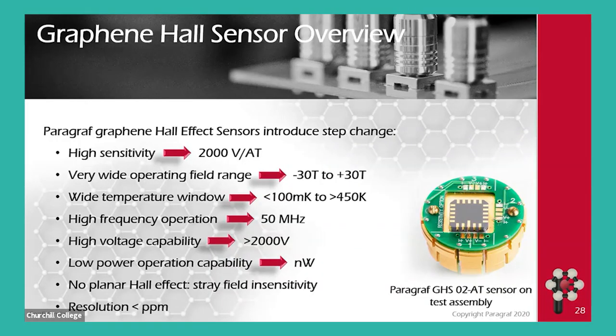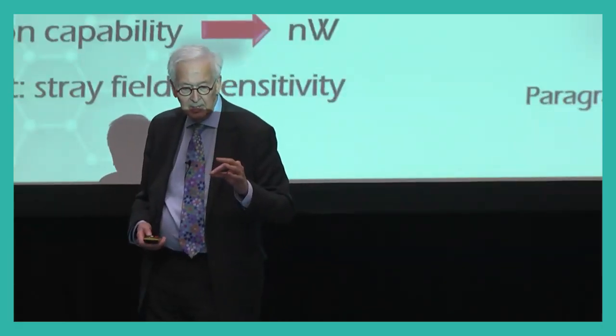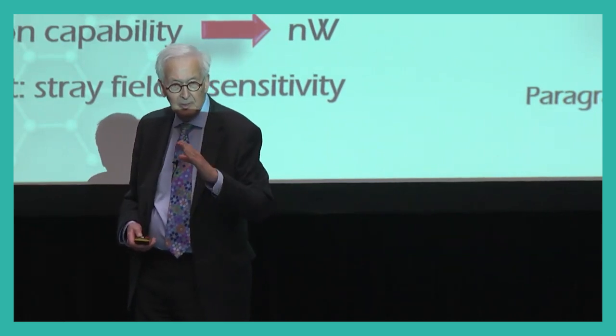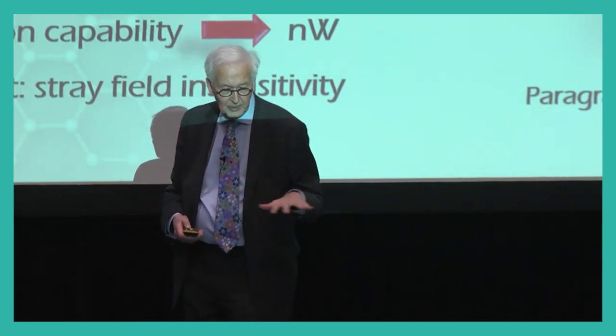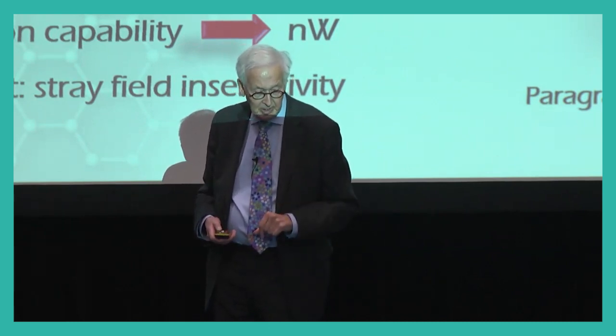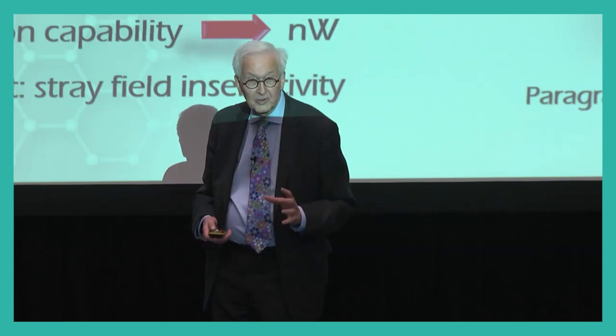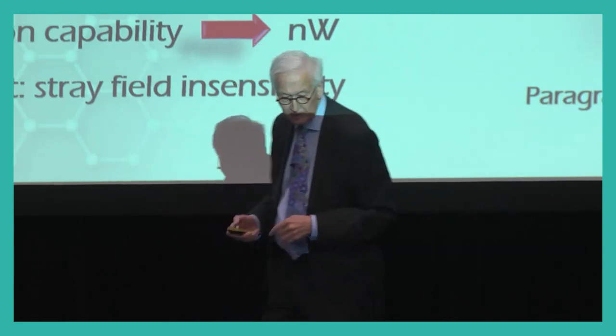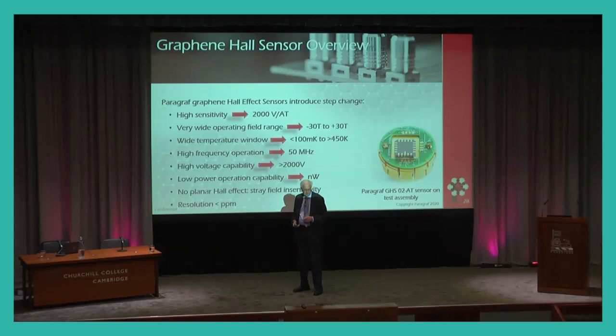High sensitivity up to 2000 volts per amp Tesla, very wide field range, wide temperature window. It can operate at high frequencies, high voltage capability greater than 2000 volts. I think for silicon, it's less than 200 volts. Low power operation, nanowatts, really low power. There's something called the planar Hall effect I won't go into, but because it's so thin, it's not sensitive to magnetic fields, you know, at an angle, as it were. And so it's very accurate for measuring magnetic fields and resolution in parts per million for measuring the magnitude of a magnetic field. And this diagram shows one of the packaged Hall sensors.